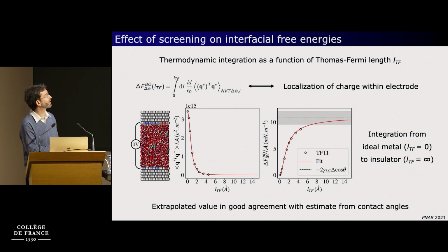And so we obtain an expression here, which is in fact very simple in terms of the charge of the individual electrode atoms. So what you need to do is simply measure the local charge on each atom, take the square, make the sum over all atoms, and this is the quantity that you then need to integrate as a function of Thomas Fermi length.